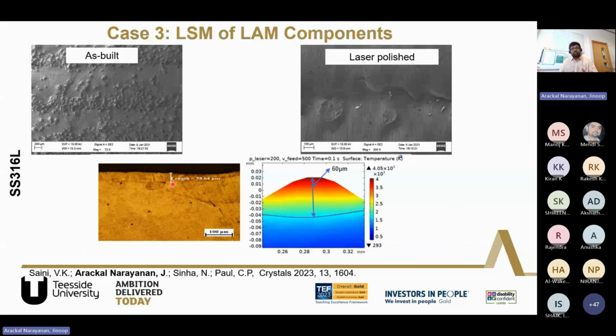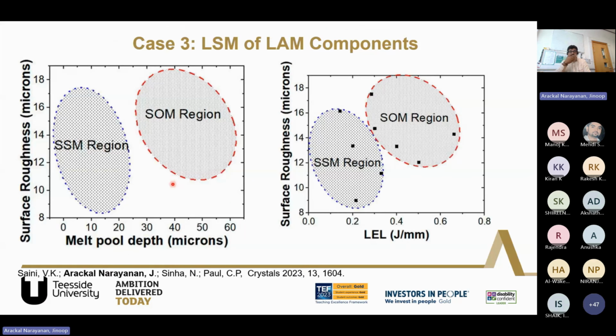We also used laser surface melting as a polishing technique. This is also one of the methods, as we didn't want to go for mechanical polishing of AM parts, to reduce material wastage. So we use laser as a tool for polishing the material, and we could reduce the surface roughness significantly by using a continuous wave 50-watt laser power.